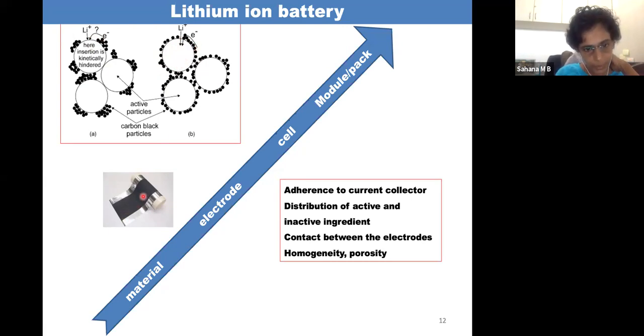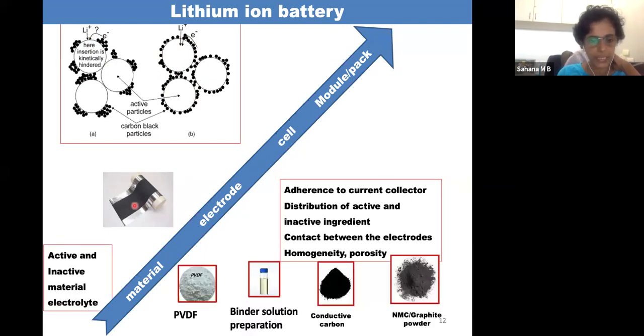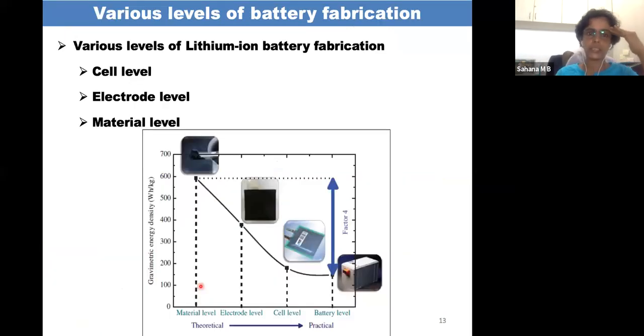Now coming back to the electrode here, as I have briefly told in an earlier slide, it has active and inactive material. Here the active material in the case of cathode is lithium nickel manganese cobalt oxide or lithium cobalt oxide, and in the case of anode it's graphite powder. And we have conductive carbon and PVDF, which is a binder, and this is the binder solution, that is PVDF dissolved in NMP solution. Now let's see what are the various levels of battery fabrication.